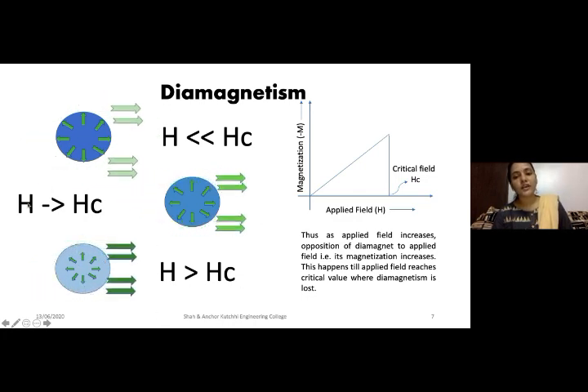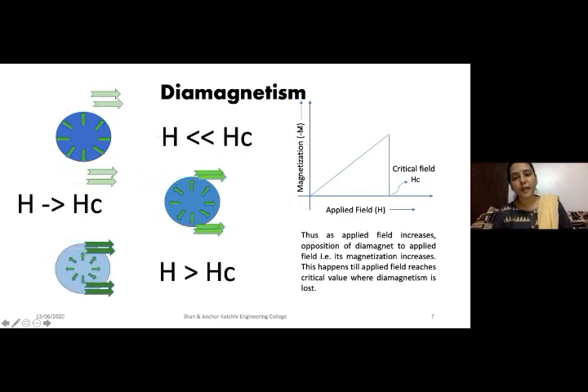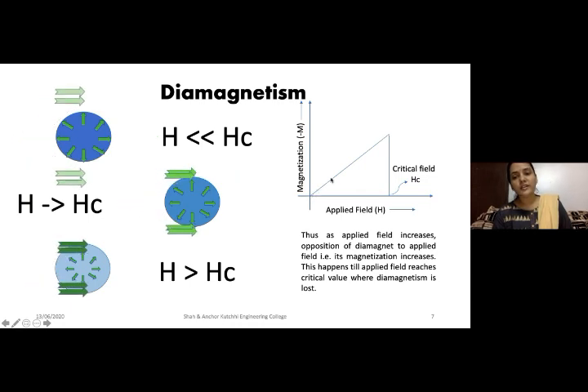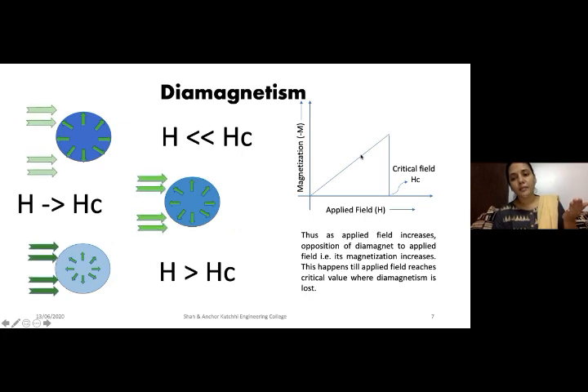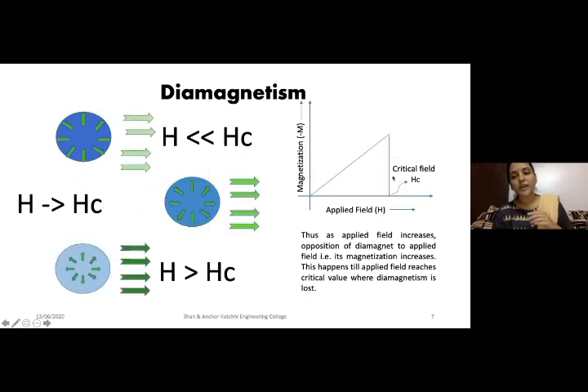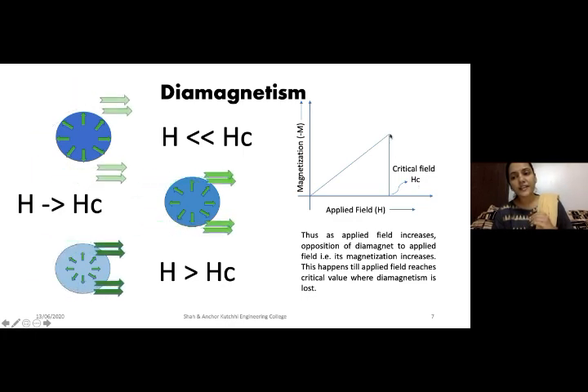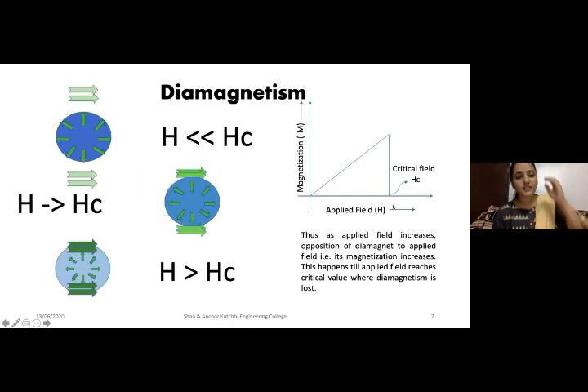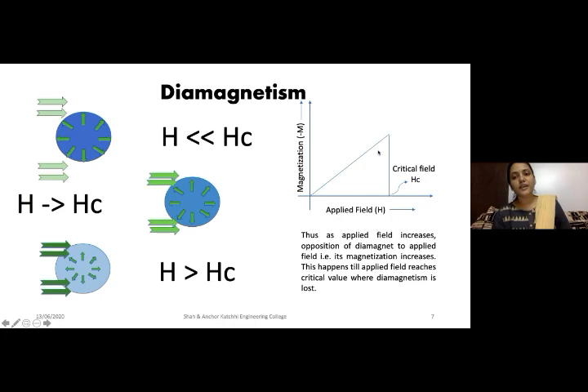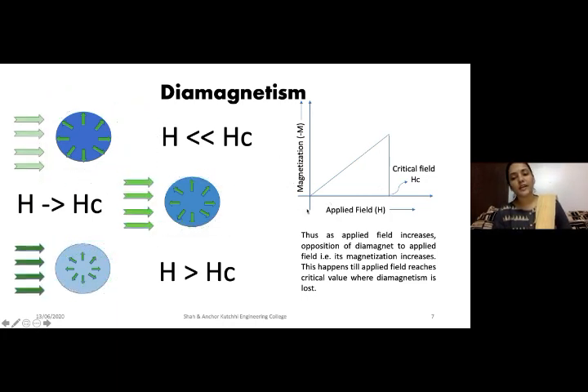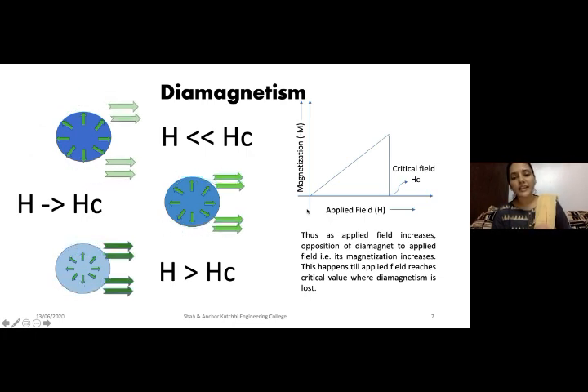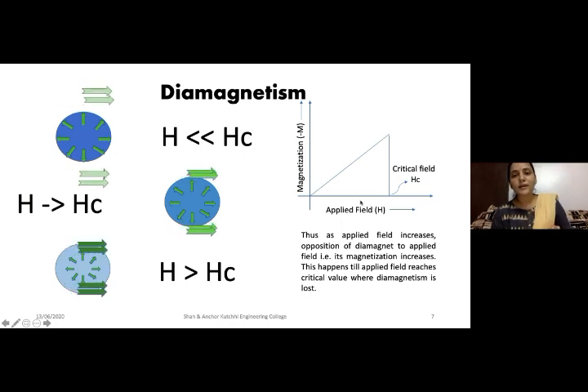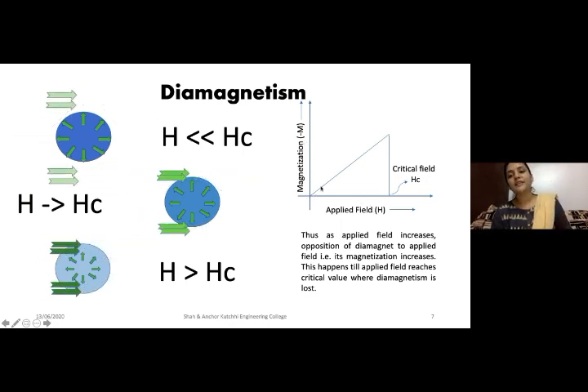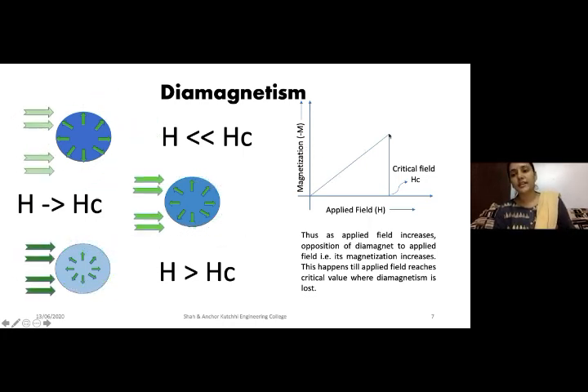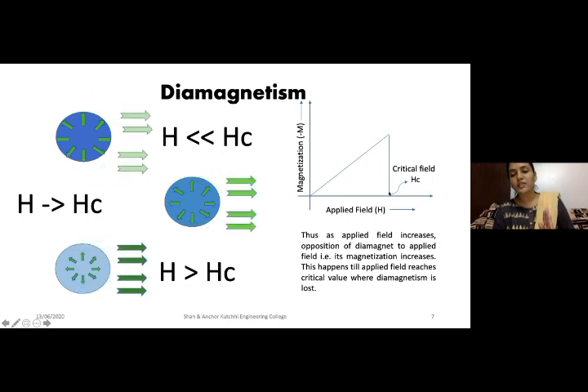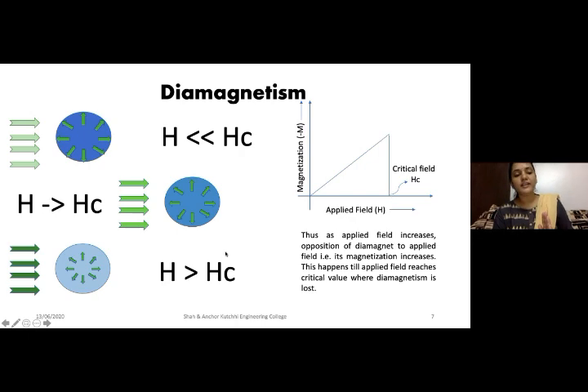So if we want to plot this behavior, let's say we plotted our applied field versus the magnetization. If the applied field goes on increasing, the internal magnetization goes on increasing. But then this will happen only till a place where we reach a critical field. At this critical field, the entire diamagnetism is lost and the flux starts penetrating the superconductor. So this diamagnetic behavior is very important for understanding superconductivity. So I'll repeat, diamagnetic behavior indicates applied field magnetizes the material in the reverse direction, and as the field increases, the inverse magnetization also increases, and this happens up to a value of the field which is called the critical field. And the moment we go to the critical field, the flux starts penetrating.